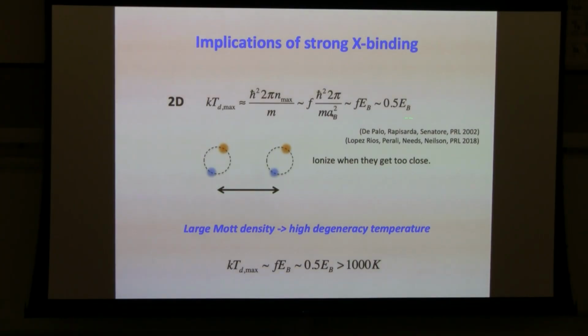So it's some factor times the exciton binding energy that will give you the maximum degeneracy temperature. And this factor was worked out by this theory paper using quantum Monte Carlo calculation to show that it's on the order of a half. So it's about 0.5. And if you plug in the numbers, a 0.4 eV binding energy multiplied by a half, and convert into a temperature scale, the maximum degeneracy temperature is actually over 1,000 Kelvin. It's actually close to 2,000 Kelvin.